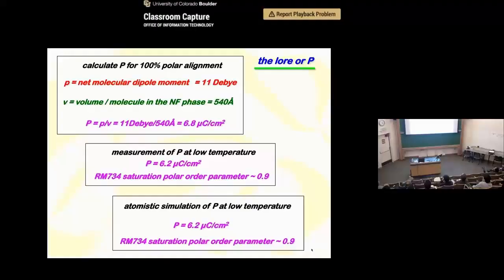We asked, suppose the molecules were all perfectly oriented, what would the polarization be? You can calculate the molecular dipole using quantum chemistry. You can measure the molecular volume from the density. And so we can calculate the maximum possible ferroelectric polarization. That comes out to be 6.8 microcoulombs per centimeter squared. So we have an incredible degree of orientational order in this phase for a liquid crystal. So we have this value, we have our measurement.